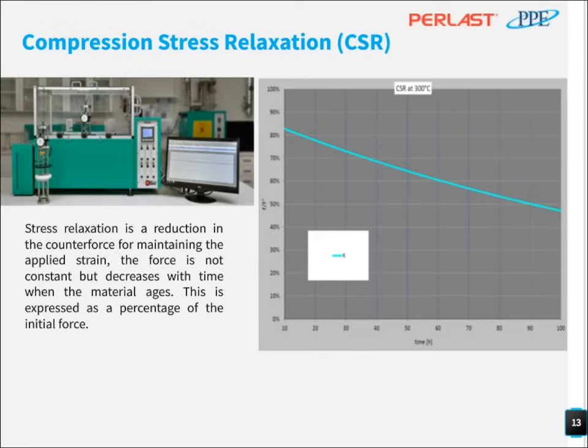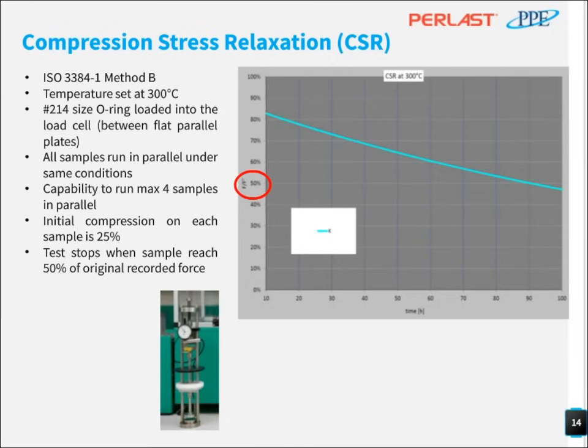So how do we do the testing? Now let's talk about the test. The standard procedures are described in this ISO standard, but I'll go very quickly. In the bottom image, you see a cell of CSR, which is basically a load cell, capable of measuring force at high temperatures. We place a standard size O-ring between the plates and squeeze it by 25%.